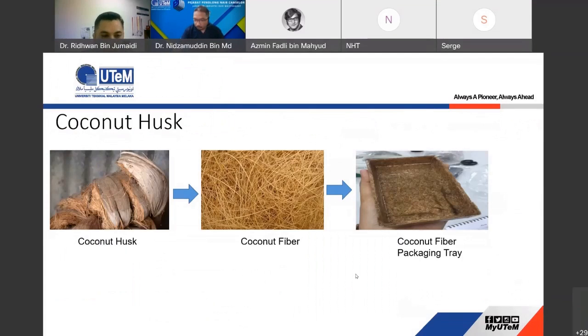And then we also tried using coconut husk, sabut kelapa. We know that coconut husk is a very strong material, and we didn't need a very tedious process to extract the fiber. We just need to use a mechanical process to separate it, and then we can collect the fibers. The fiber has also been used to develop a packaging tray as well.